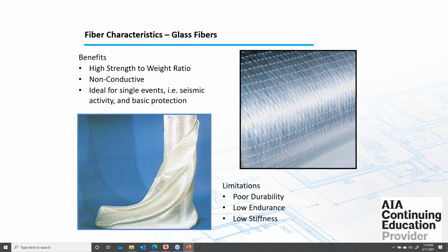The reason for that is glass is susceptible to creep rupture. So as it's placed under constant load, it really starts to stretch and ultimately will rupture much more rapidly and prematurely than you would see from the carbon. So it's just really not ideal. It doesn't have that durability and endurance that the carbon has. So we try to avoid it for flexural or shear strengthening, where it's just under constant load.